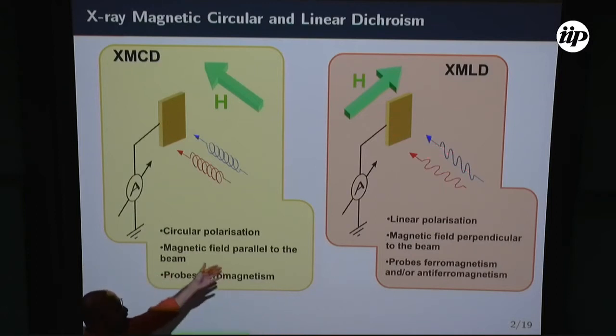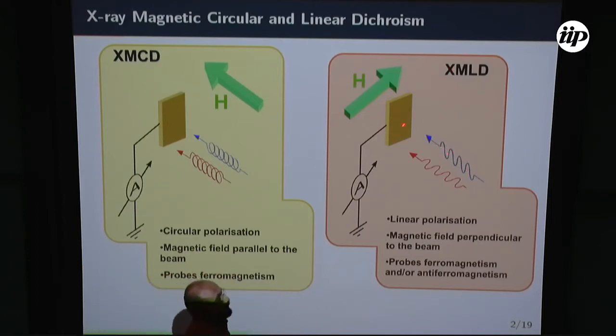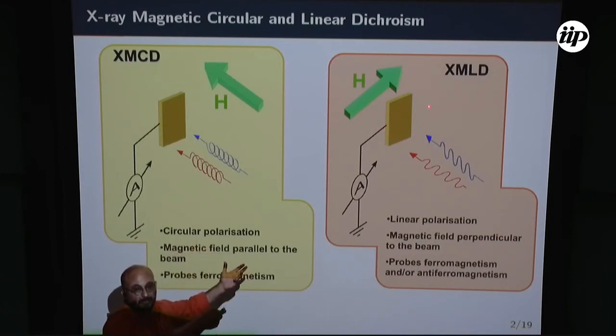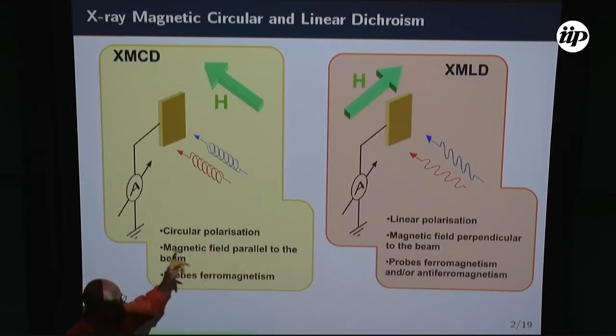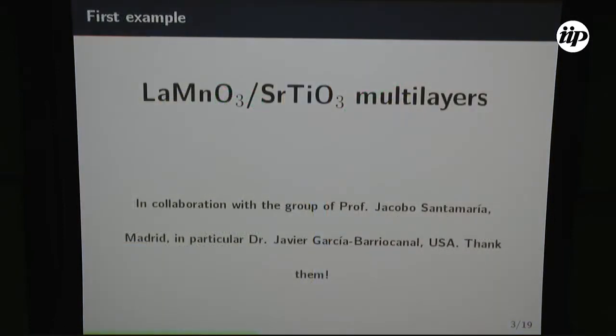And this is the X-ray magnetic linear dichroism. It became very, very used because it's very sensitive, for example, very useful for antiferromagnets, which normally are very difficult to probe. But you don't need a magnetic field to make any anisotropy. It can be a crystalline anisotropy, and you'll be sensitive to it also. And that's important. I'm going to use this property in this example. So what I'm going to do is illustrate the potential. I hope you will